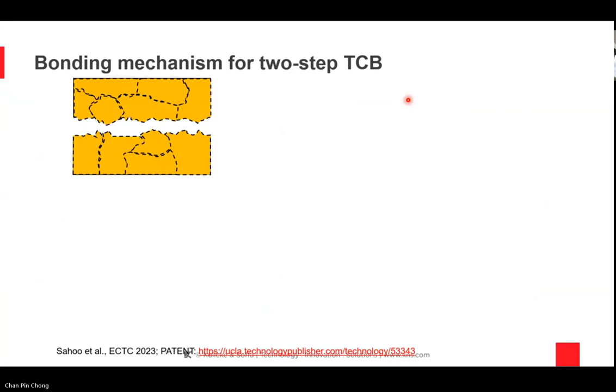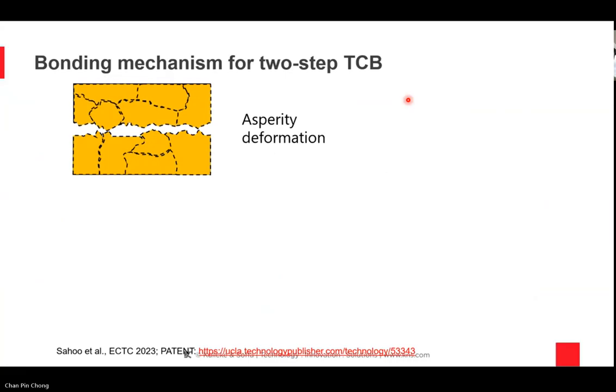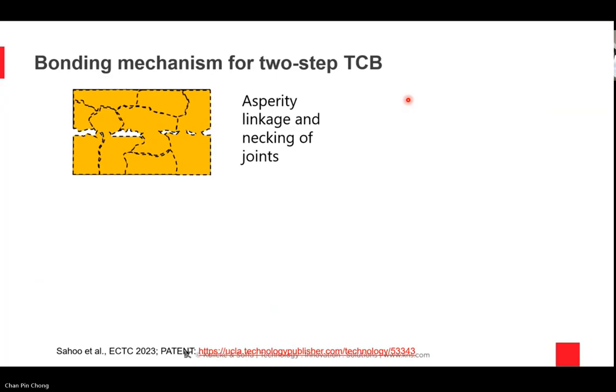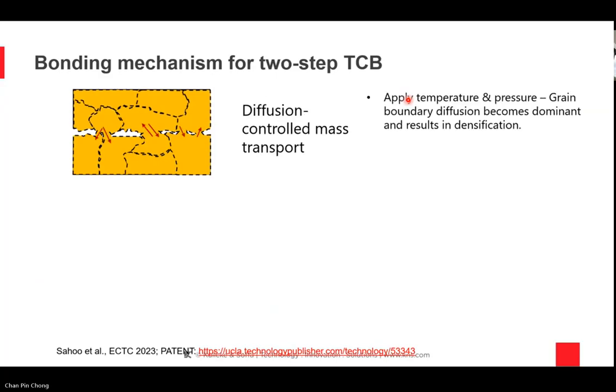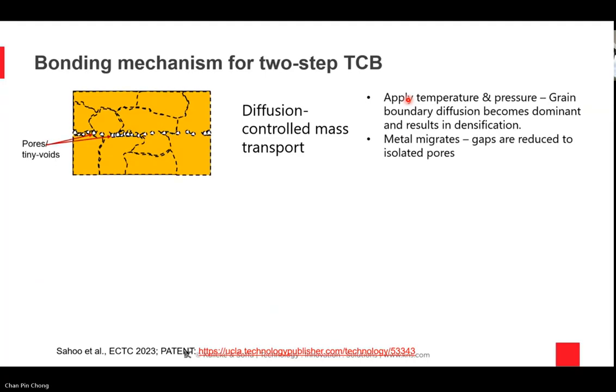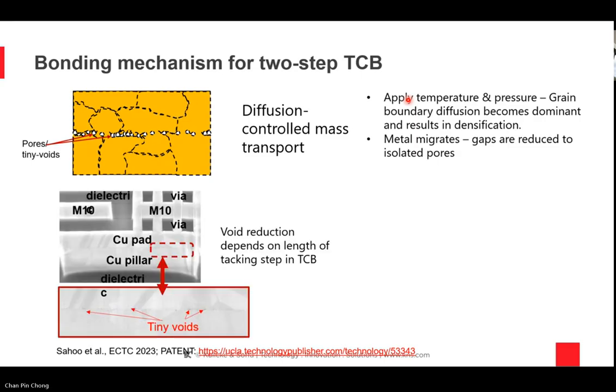So what are the bonding mechanisms? When you bring this down and make contact, wherever you make contact, with temperature you create a diffusion controlled mass transport. When you apply pressure and temperature, there's also grain boundary growth. And wherever there is no contact, there will be a void.